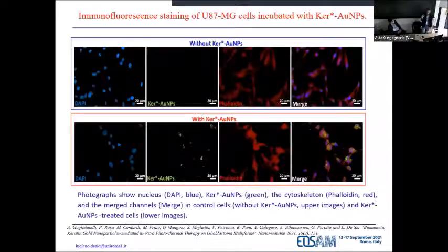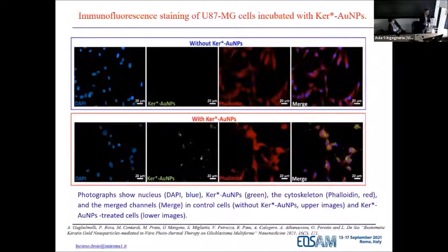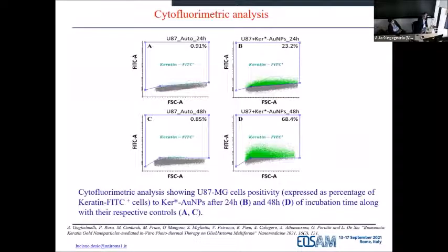And just to give you an idea, those images were acquired once we washed the cells. So in other words, we are mimicking the flow of golden nanoparticles through the bloodstream. So it means that those particles are either stuck on the cell surface or maybe have been internalized. Something else we did, we tried the number of cells positive to golden nanoparticles, to keratin. And you can see that after 48 hours, 70% of cells are loaded with keratin-based golden nanoparticles.